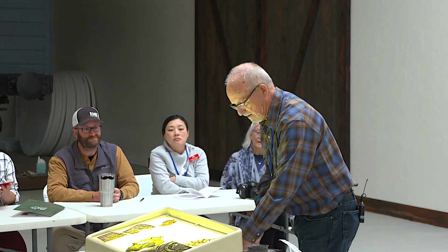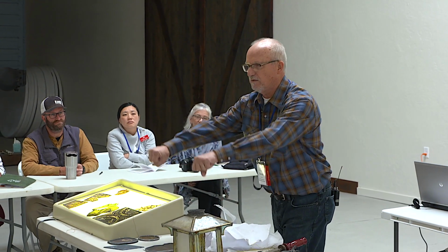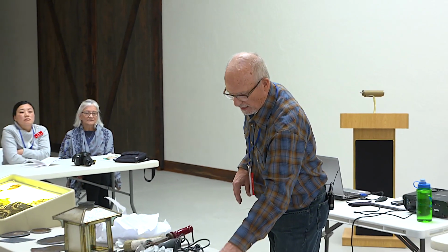And the reason for that is anytime you take glass out, say you scoop glass out of your furnace and throw it on a steel table and take a steel rolling pin and squeeze it out into a sheet of glass, you get the texture of the roller and the texture of the steel table. And the glass is, say, 1500 degrees. When it hits that cold steel, it gets a skin on it. It starts to harden real quick. And that skin starts to coagulate. And the inside of the sheet is still hot and moves a little bit. So then you get this real wrinkled, strange texture. And that's even on the smooth side.